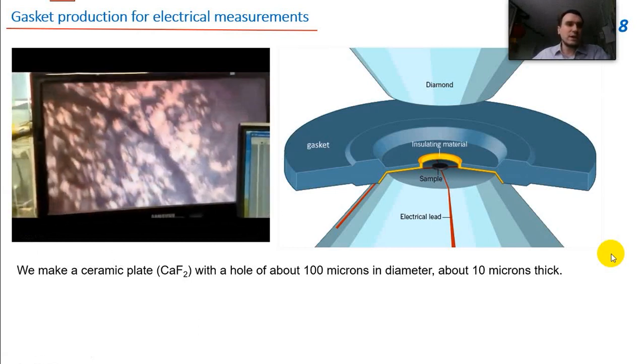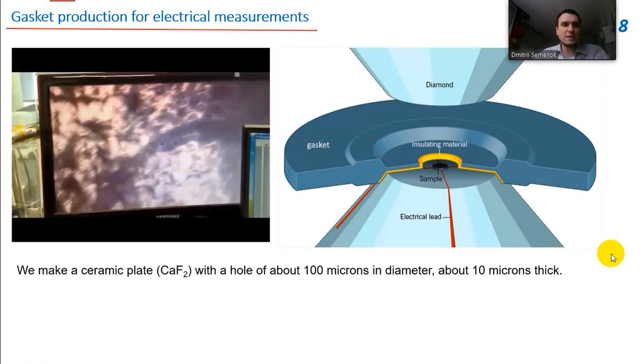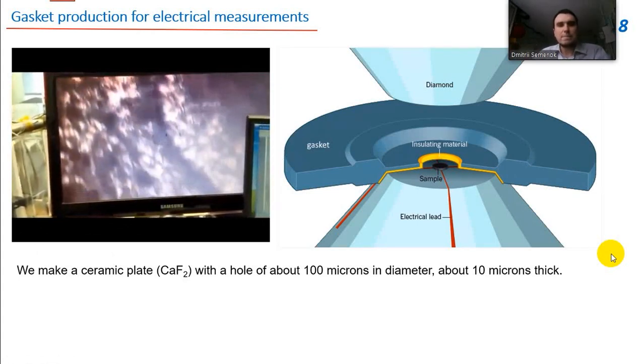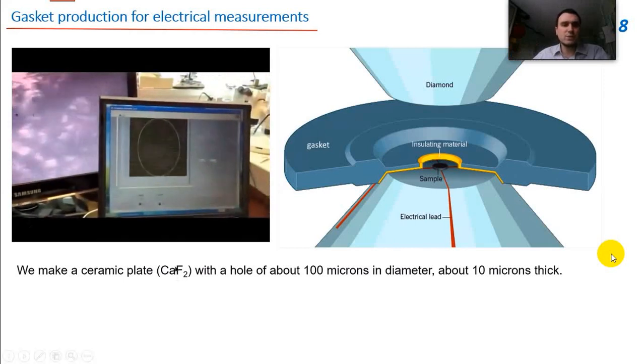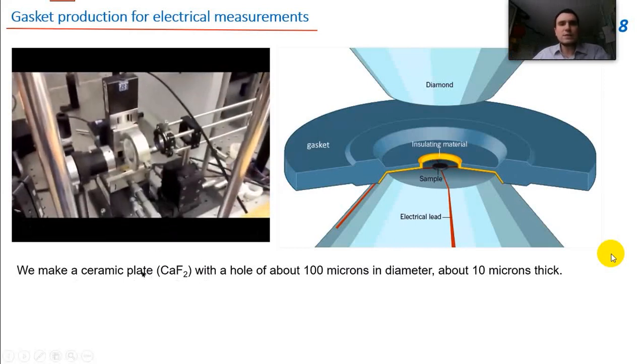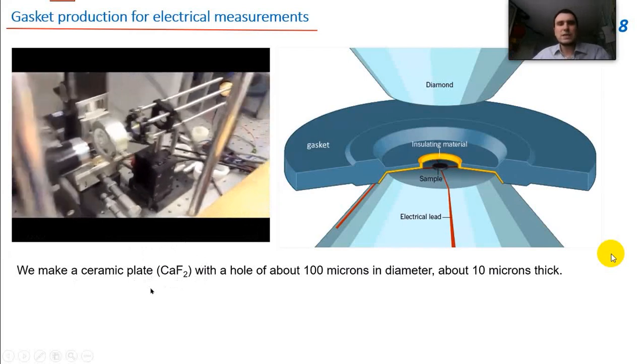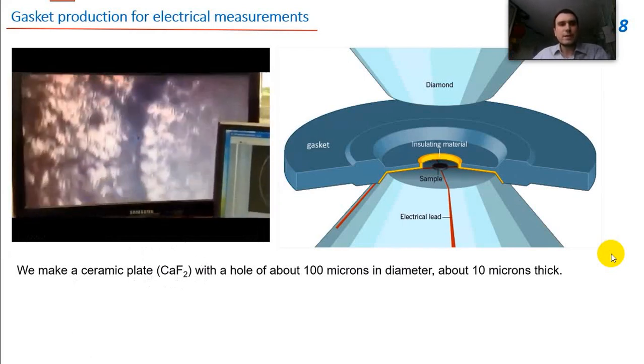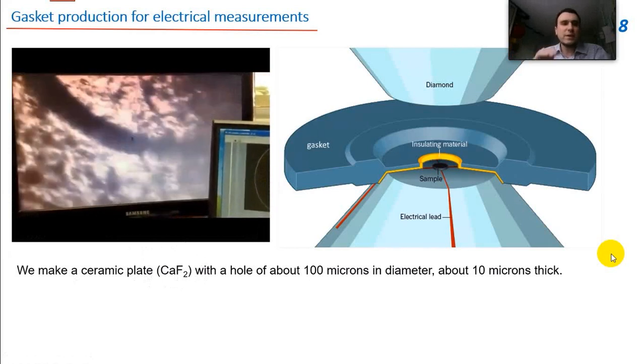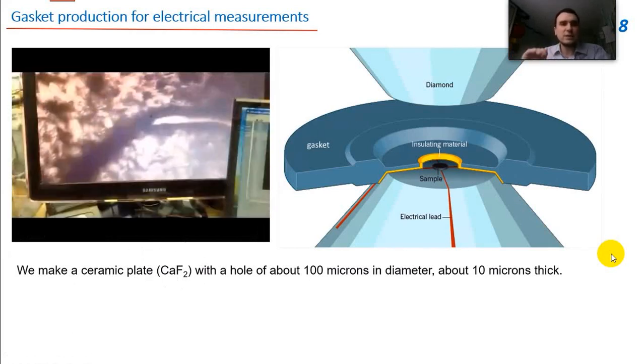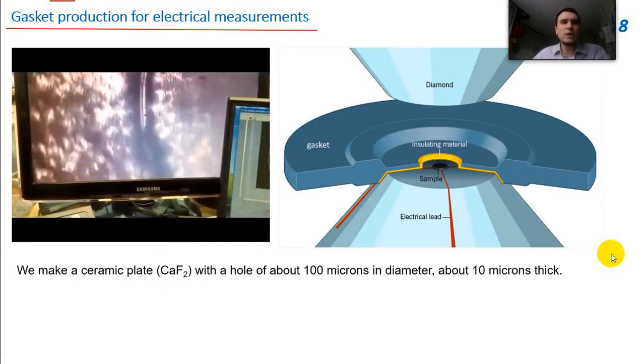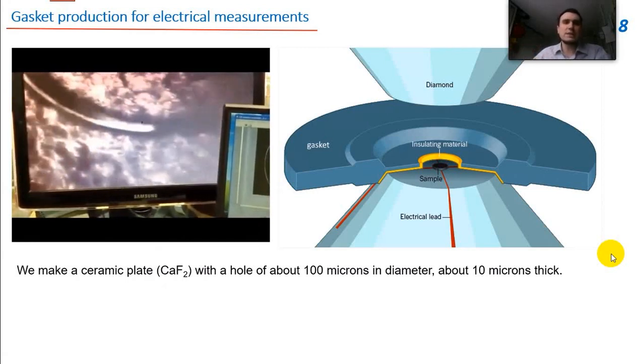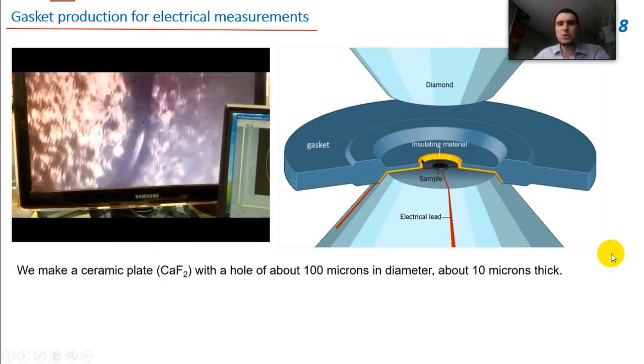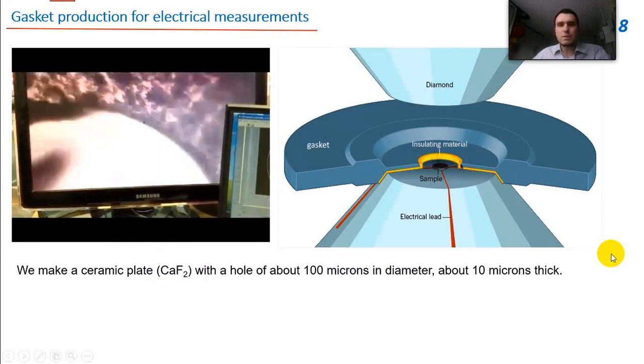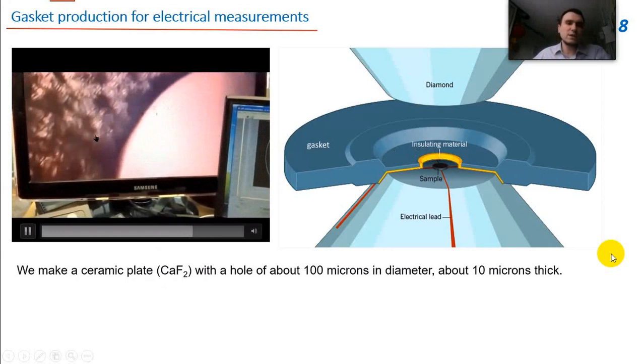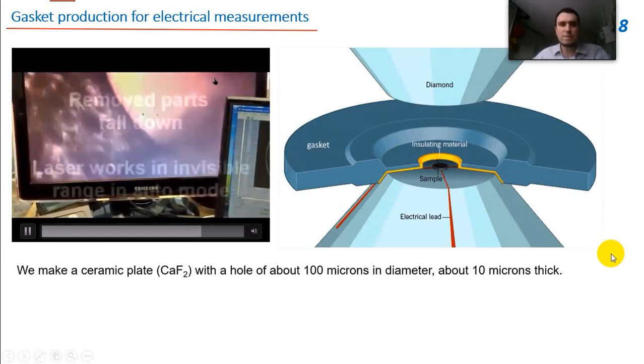You see on the video how the ultraviolet laser makes a kind of channel in the thin ceramic gasket, which consists of calcium fluoride in this case. The thickness of this gasket is about 10 microns, so it's very precise work. Step by step, we make this channel deeper and deeper, and finally we cut a hole for the high pressure chamber where we can place our sample. It's shown in yellow in the right picture. So now the process is finished, and we can go to the next stage of preparation.